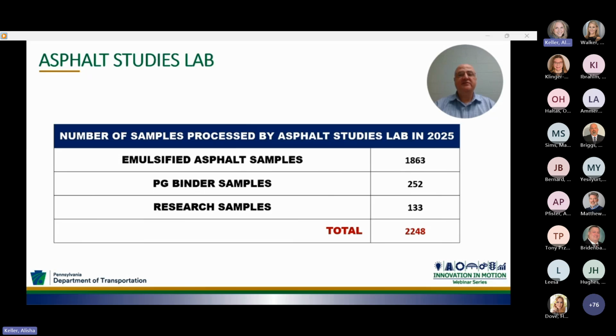Last year, the Asphalt Studies Lab tested a total of 2,248 samples. As you see on this slide, the majority of these samples were emulsified asphalt samples, with 1,863 samples, followed by 252 PG binder samples and 133 research samples.